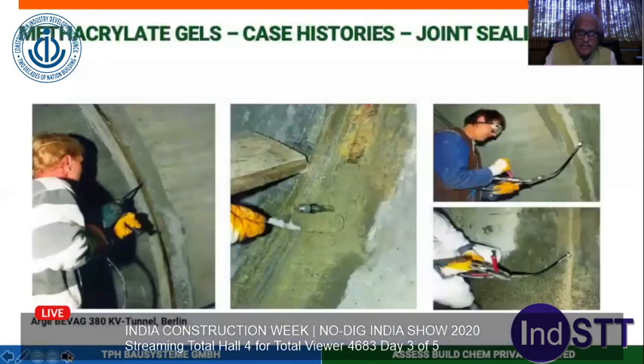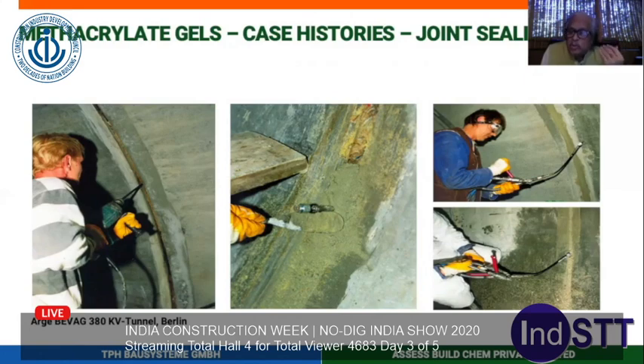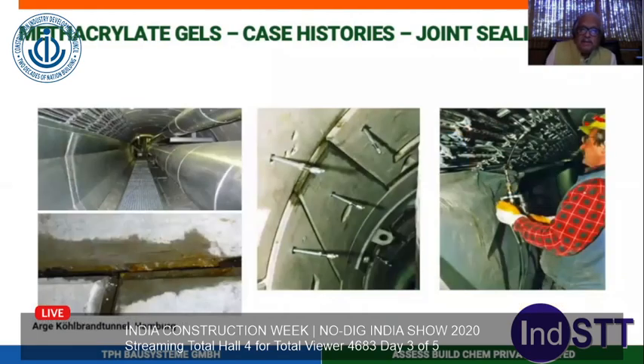which will set inside. This material is also very, very important in precast joints. In precast joints of the segments, you already have gaskets put inside. However, due to constructional problems, these gaskets are not 100% waterproof, and the water starts coming in through the gaskets. But please remember, at the end of the day, they are joints. You can inject through the joints by needle injections.